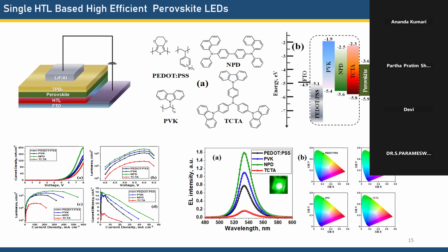Here these are the four molecules you can see: PEDOT:PSS, NPD, PVK, TCTA. What we did was change all the layers, and see how the hole and electron go inside the device. You can see the current in the bottom first figure. The current density versus voltage, luminescence versus voltage, luminescence versus current density, and current efficiency versus these are all our electrical parameters. It follows the diode behavior exponentially, and the luminescence brightness we got is almost more than 24,000 candela, and we got very good luminescence efficiency and external quantum efficiency.